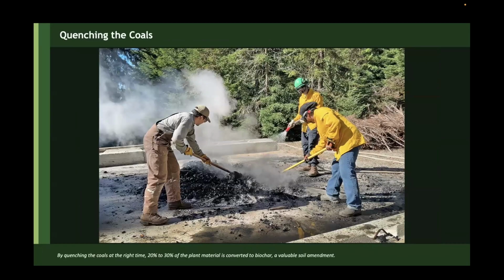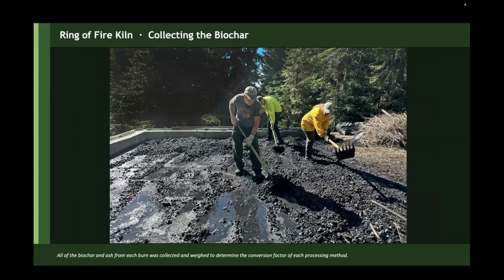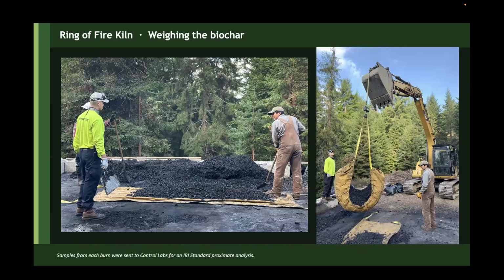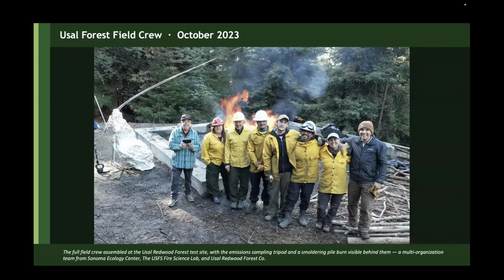At the end, we would extinguish the coals when we were doing the conservation burn or the kiln burn, rake it out. Here, this was a kiln burn showing that there was a much larger amount of biochar produced. These kilns can produce very high quality biochar. We've had it tested by labs, control labs in Watsonville, and can get up to 85, even 90% carbon. And then, as Karen mentioned earlier, we put it into this great sling and weighed it to make sure that we understood how much biochar was created. And I'm going to let Karen take over here again, just kind of explaining the last couple slides.